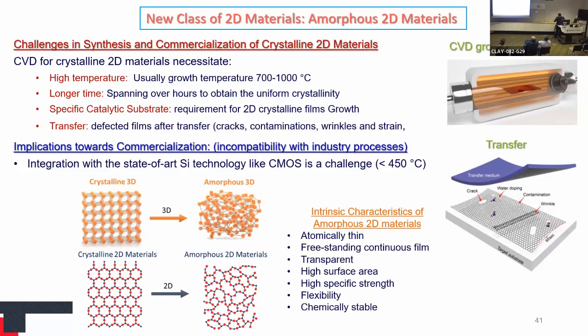So that's where we can think of other materials, because we already have crystalline 3D to amorphous 3D, but we didn't have much on amorphous 2D materials. While we keep the main properties of 2D materials, like atomically thin, freestanding, transparent, surface area, all these properties intact, we have to lose a little bit of crystallinity. So if we have a 2D amorphous material, we still can get all these properties, but just the crystallinity will be lost. What about the electrical properties?